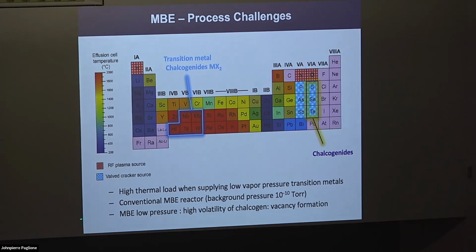Okay, so just to think about MBE from sort of the components in a reactor. Usually this is happening at ultra high vacuum, so something like 10 to the minus 10 Torr, right? So you have, in order to have the mean free path sufficient to have this molecular beam from the K cell and so forth, right? So it turns out this low background pressure is actually a problem for synthesis of these transition metal dichalcogenides, because remember that the chalcogen has extremely high vapor pressure, right?